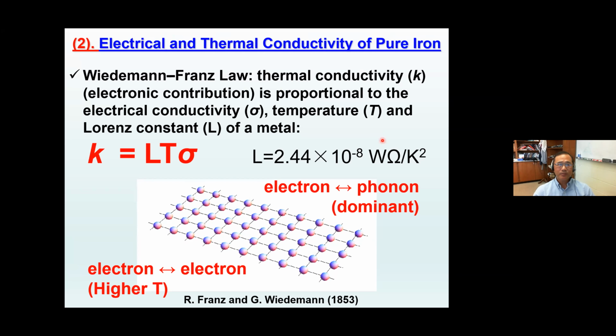All right, so how do we actually approach this problem? Let's think about what is contributing to the electrical and thermal conductivity of pure iron to start with. Based on the Wiedemann-Franz law for pure metals, the major contributor to electrical and thermal conductivity is the electronic contribution, or the electron-phonon scattering. So you can actually use the Wiedemann-Franz law to relate the thermal conductivity to the electrical conductivity. And this number here is called the Lorenz number or Lorenz constant, which is this value listed here. And this equation here is also temperature dependent.